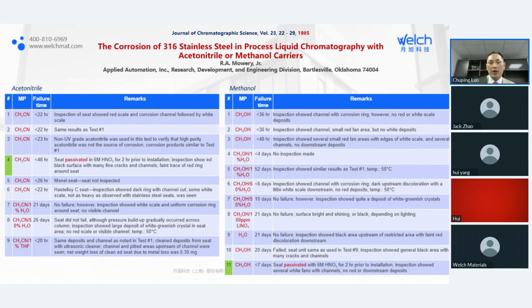Of course, in this set of experiments, different kinds of surfaces were used. From the left side of the table, numbers 1 to 3 are stainless steel tubes that weren't treated very well. But number 4, the tube was passivated by nitric acid. This is the typical way in today's LC systems, where all the stainless steel is treated this way. People believe that by using nitric acid to treat the surface, you get a very dense metal oxide that can protect the surface, make it inert, and keep you safe. But actually, it is not.